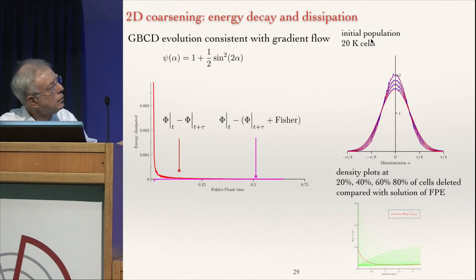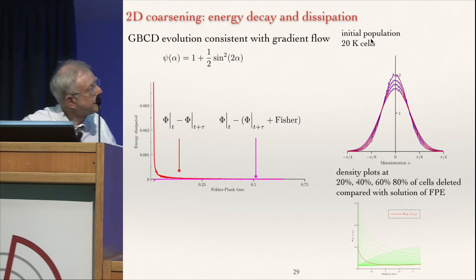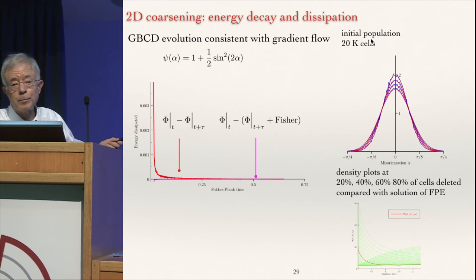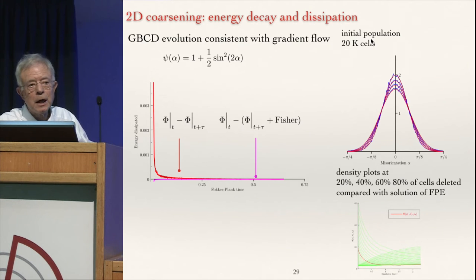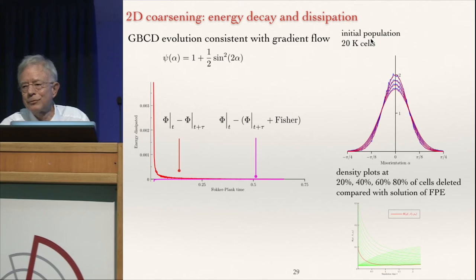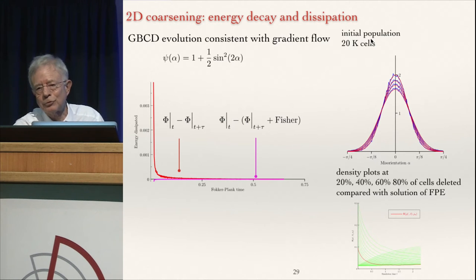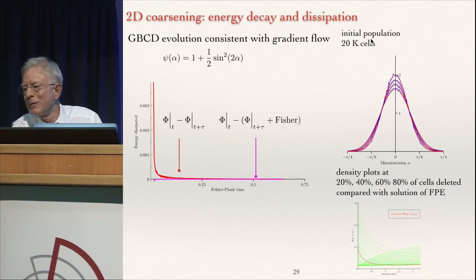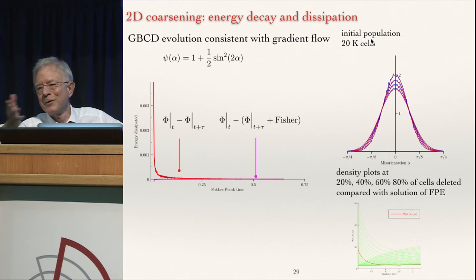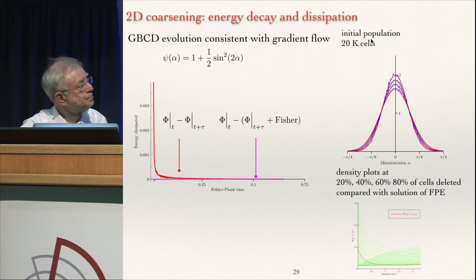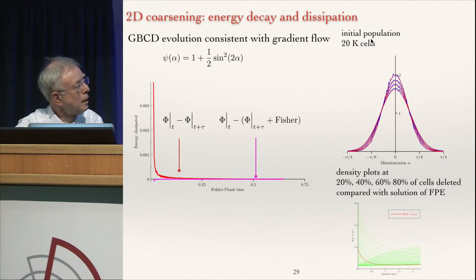And they're compared with the red curves. They're in blue, and the red curves are solutions to the Fokker-Planck equation at those times. And you can see how miraculously this 2D coarsening system, whose movie you saw in the previous slide, tracks a solution of the Fokker-Planck equation. This is astonishing, I think. I can say that it's not exactly my work, it's the work of a whole group of people, but I think this is very, very interesting and different. And here's the relative entropy picture, which I just repeat for you.